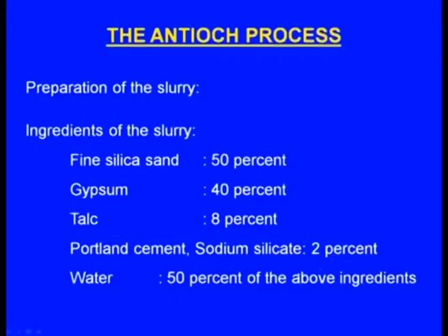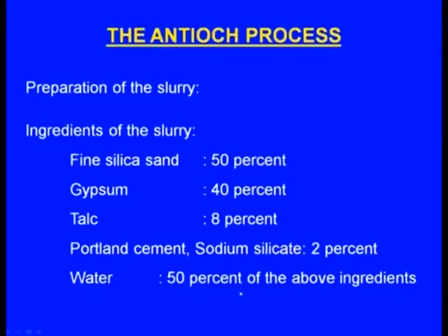In addition to that, water will be 50% of the above ingredients. You see, even the proportion of the ingredients is different. Here there is a major difference. Fine silica sand will be 50%, gypsum 40% and talc 8% and this is the 2%. In addition to that, there will be water 50% of these overall ingredients. Then all these will be mixed together.